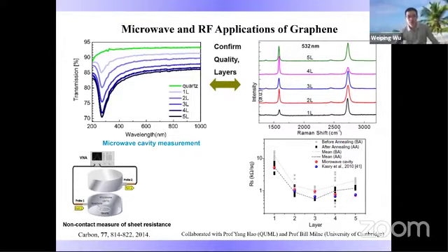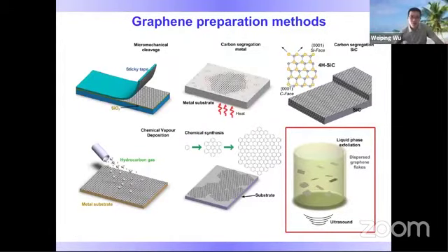Beyond these vacuum processes, graphene samples can be prepared by a range of methods, but the most important include the silicon carbide method and chemical synthetic methods. We can also use a very simple physical method, using graphite as the starting material, putting the graphite in liquid or water, and using ultrasonication as a power source to exfoliate the graphene into the solution.